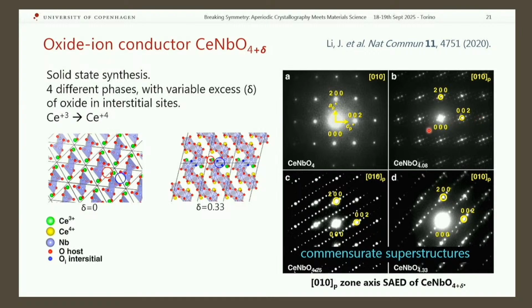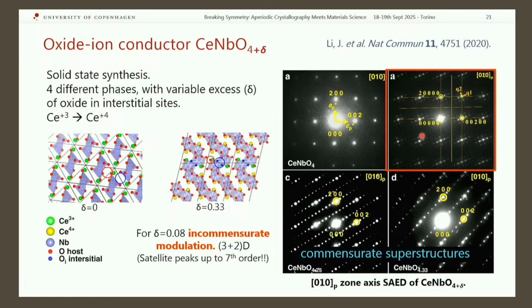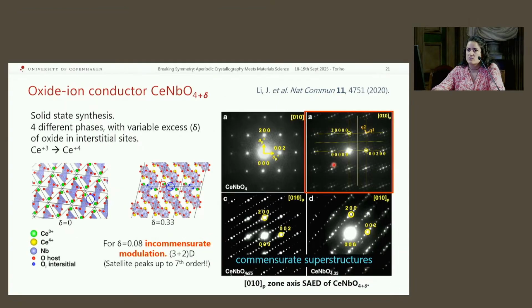So these are our satellite peaks that we need 2 additional vectors to index all the peaks. So in this case, we have to use 3 + 2 dimensions. And it's an incommensurate modulation. And actually, this sample diffracts exceptionally well. You can see satellite peaks to very high order.